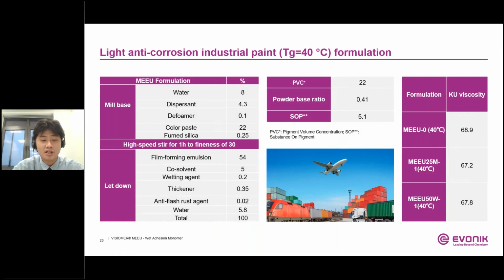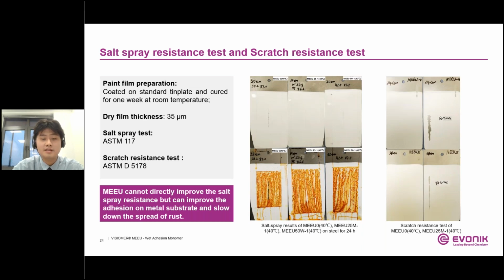And similar to the construction paint formulation, we redesigned the industrial paint formulation with a PVC of 22. And in this formulation, we also added an anti-flash rust agent. The viscosity was controlled between 67 to 69 KU. In the case of industrial paints, the anti-rust and scratch resistance are critical properties. So the salt spray and scratch tests were performed to investigate the performance of MEEU.